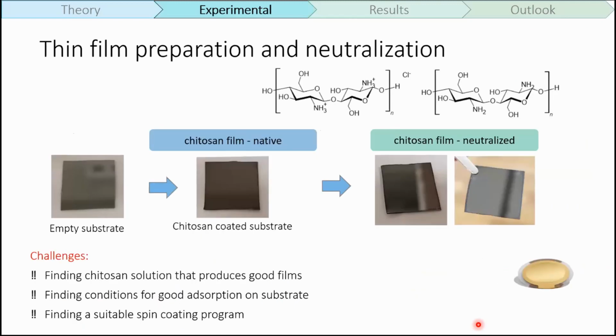After we prepared this Chitosan film, we then had to neutralize it, because without neutralization, our film would easily dissolve in water. With this neutralization step, we achieved that the film was actually stable.